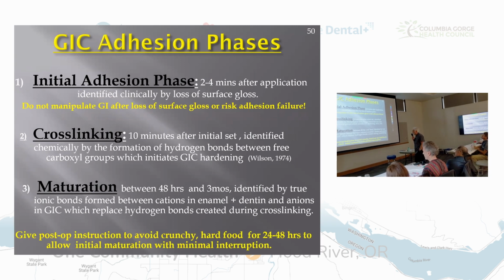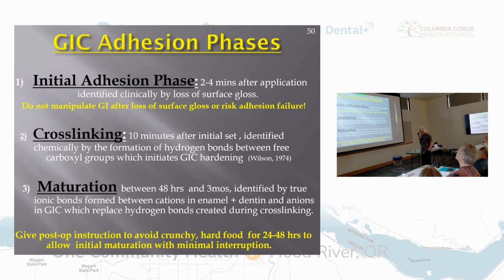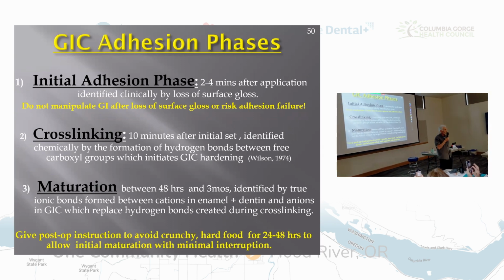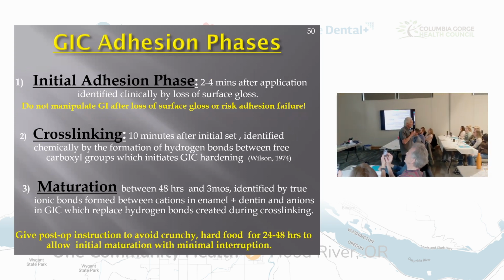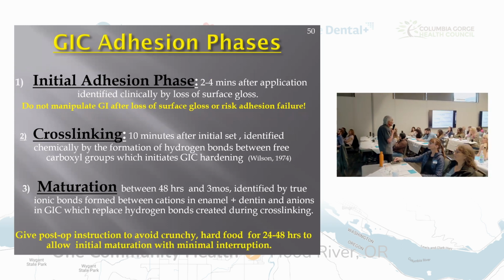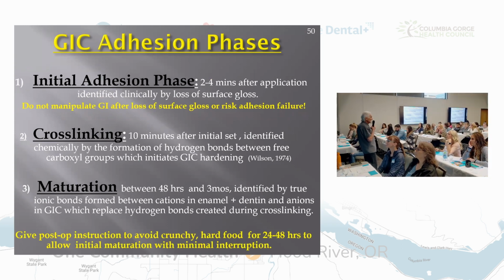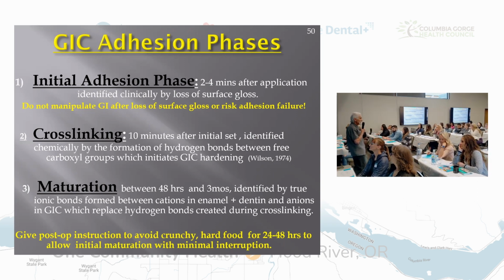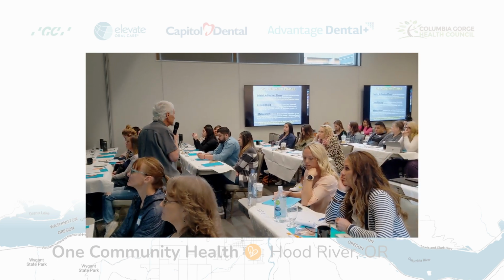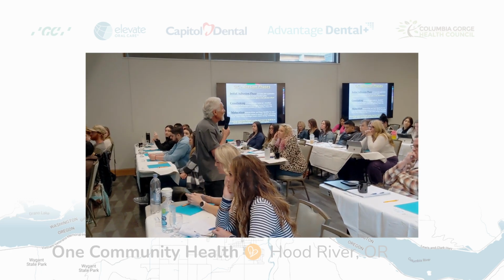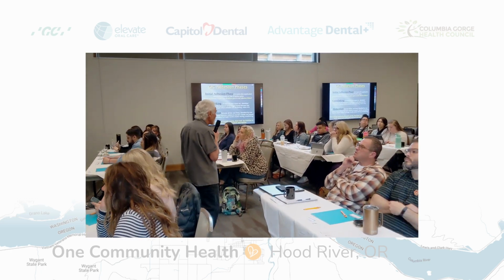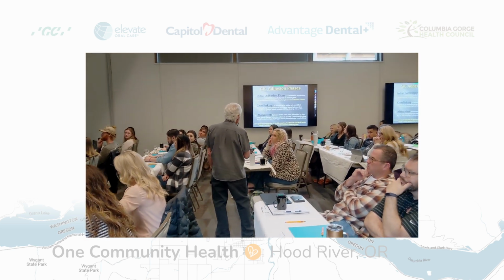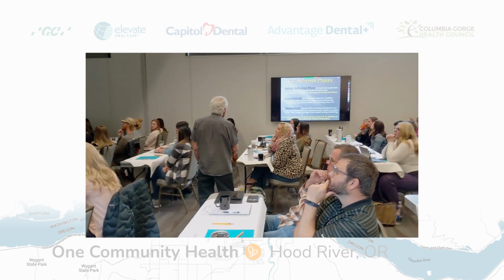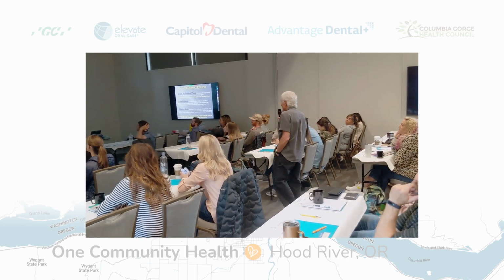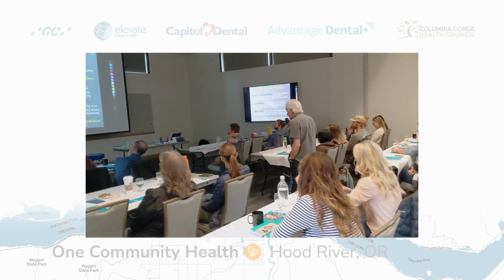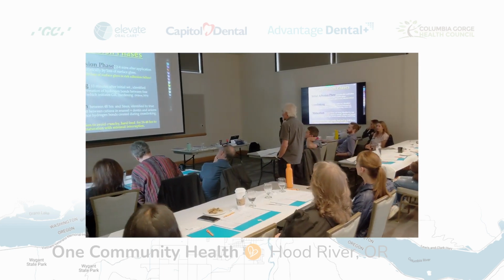There are 3 phases I want you to memorize. There is the initial phase. It happens within 2 to 4 minutes after application. It's identified by a loss, clinically, of gloss. After it loses its gloss, you are done with the initial phase. And manipulating it any further is the kiss of death. You know what you do too much of, guys and gals? You manipulate too much. Because you could. Because you had a light to cure the composite. With glass ionomer, you don't have the luxury of manipulation anymore. Because if you manipulate after it loses its gloss, you risk adhesion failure. So when dentists tell me it didn't work, it didn't adhere, I say you did not honor step number 1.